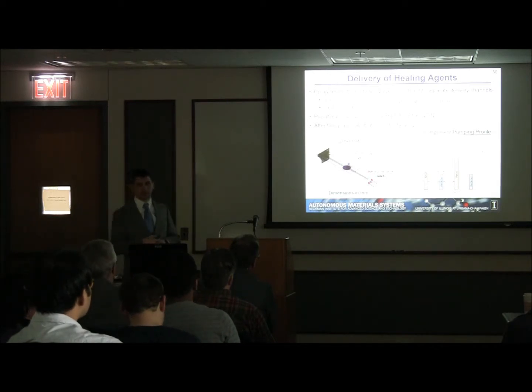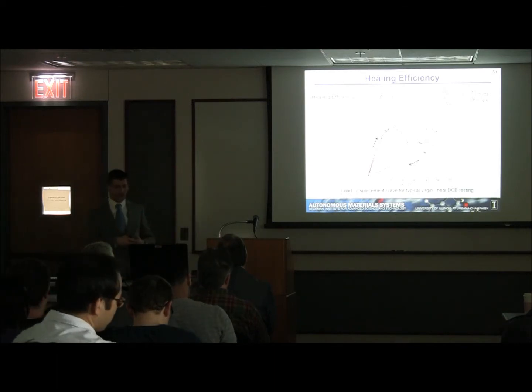And so his particular delivery scheme looks something like this, where he's alternating resin and hardener and giving a little bit of wait time between each one of those pulses. So then after we fill all the damage, we allow 48 hours at room temperature, or 30 C, which is sort of the control room temperature, for healing to occur. Then, after healing has occurred, we can reload those samples and get a measure of the healed critical strain energy release rate. Then we can define a healing efficiency metric, which is the ratio of the healed to the virgin critical strain energy release rates.